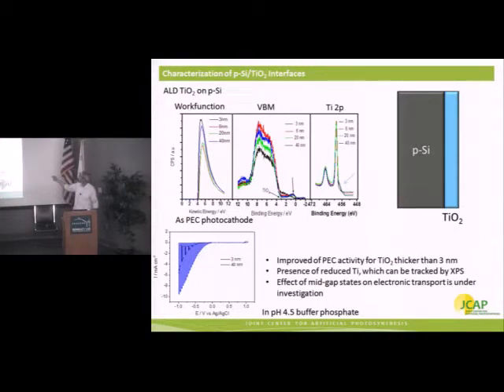So here's an example of a p-type silicon with TiO2 on the surface. We've done photoelectron spectroscopy that can verify the work functions of these materials as well as the densities of states near the valence bands. So the valence band density of states is shown here. This onset here to the large feature in the spectrum is the TiO2 band edge. We also have a large density of states within the band gap, which we're currently investigating. This shows up as reduced titanium in the titania film.